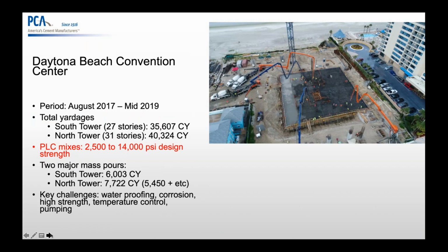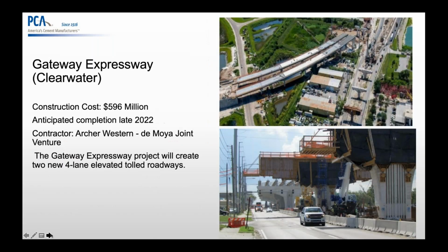Another high-profile project, we're using Portland limestone cement in Daytona Beach. Over 75,000 cubic yards of concrete was poured with all kinds of mixes ranging from 2,500 PSI to 14,000 PSI. So a very nice project, very high profile, and they've had great success on it. This is an ongoing project that you can drive through.